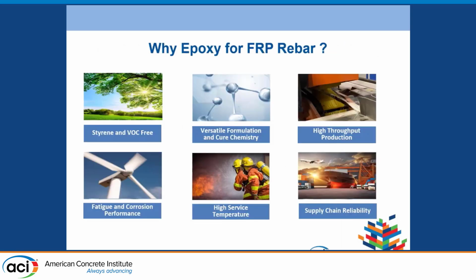So why epoxy for FRP rebar? In the last 2 years, we have been promoting epoxy systems for FRP rebar applications. The biggest advantage of epoxy for FRP rebar production is the styrene-free, or VOC-free, feature. Epoxy systems do not require styrene as a resin diluent, which provides a better working environment. Epoxy has a broad choice of monomers and curing agents, so it can provide versatile formulations. Without the low boiling point resin diluent, the epoxy system can be cured at a much higher temperature compared with other thermoset resins like vinyl ester or polyester. By tuning the system, it can also achieve fast reactivity, so epoxy can achieve high throughput production, especially for the rebar process.